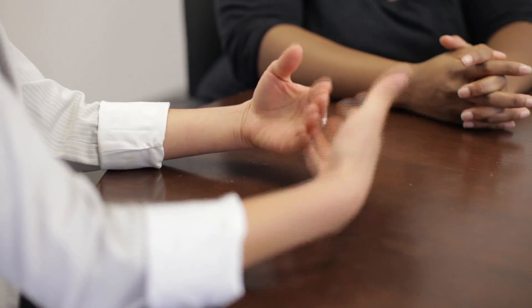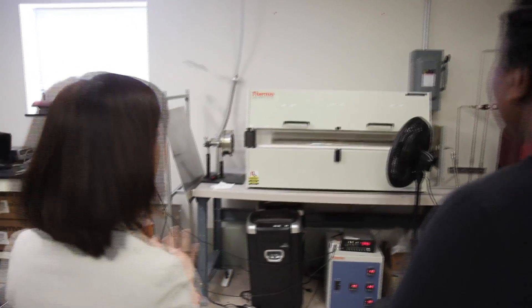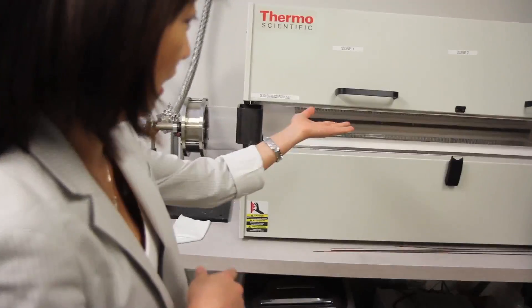One of the main current hurdles in the industry is that graphene is being explored for applications in many different areas — flexible displays, supercapacitors, batteries, and biosensors — and actually making high-quality graphene is one of the key things to enable all of those applications. Here at Graphene Frontiers, we grow our own graphene material. We have a furnace that goes up to 1000 degrees Celsius — this is the furnace where we grow the graphene — and we flow different gases through it, which causes carbon to deposit onto copper, forming a single layer of graphene.